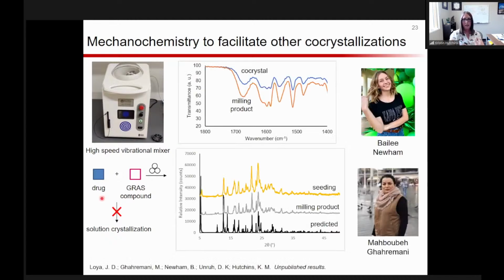And now what we've seen is by milling across the board, we can actually do milling and have by IR really nice correlation to the co-crystal. The milling product in this case is actually a co-crystalline solid directly. So we don't have this oil happening in between. We actually make co-crystal immediately after milling. And we now have this high-speed vibrational mixer that we are using as well from FlackTek. And so we can actually do this milling in a period of 5 minutes instead of an hour, at much higher RPM. So our throughput is quite a bit faster. We can probably do experiments faster than we can collect data to characterize them at this point.